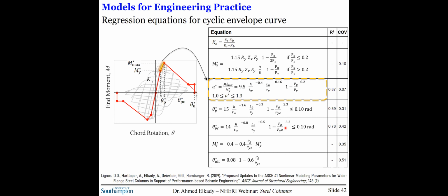The model also captures the variability in the post-yield slope with respect to the column parameters and the axial load. And this is compared to the constant slope that's used in ASCE 41, which is 3% of the elastic stiffness. So here you can capture this variation in this slope. At the same time, rather than having a sudden drop in your moment-rotation curve once you reach your capping strength, which is the case in ASCE 41, here the model captures the gradual post-peak slope or post-local buckling slope, which can also help with numerical convergence issues when you are doing analysis. But most importantly, it captures better the overall behavior of your component.